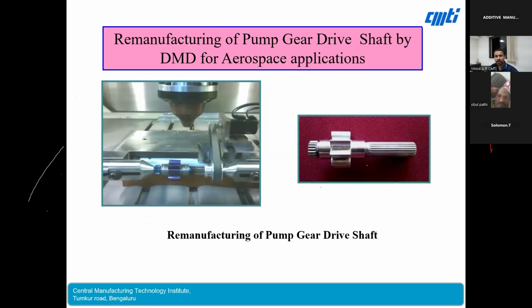This we did for HAL engine division, wherein there is a pump drive shaft. Here, in the two shoulder areas, it will be wearing out by around 0.5 mm. Coating by hard chrome plating was initially carried out, which was delaminating. When we are rotating a rotary part and you do coating by a hard chrome electroplating technique, it was peeling off.